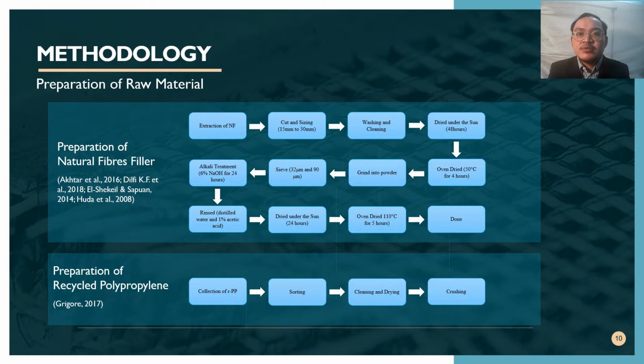The preparation of recycled polypropylene is based on a previous study done by Grigore in 2017. The first step, polypropylene is collected from the recycling center in Melaka. Then the plastic must go through a sorting process to separate the polypropylene from other polymer plastic. Then the polypropylene will be cleaned to eliminate any oil, dirt or contaminant that may affect the result. After that, dry the polypropylene in the dryer at a temperature of 80 degrees Celsius for 1 day to remove any moisture. And for the final step, the polypropylene will be put into a crusher machine to crush it into granulate or pellet size for the fabrication process later on.